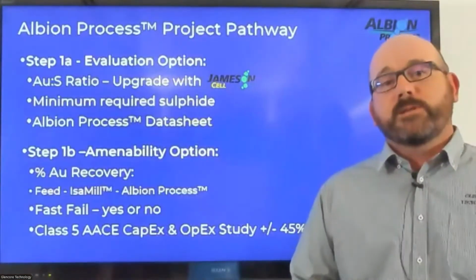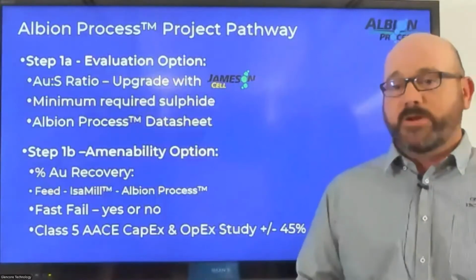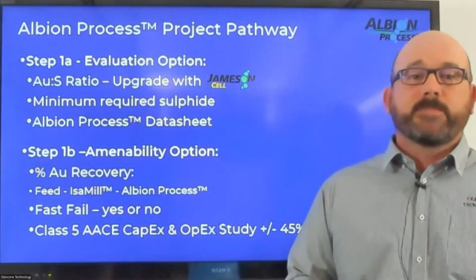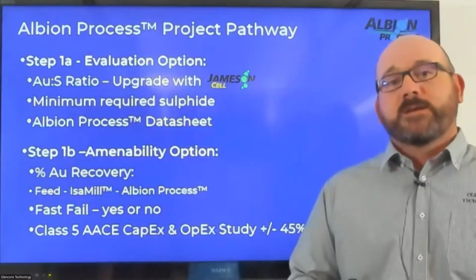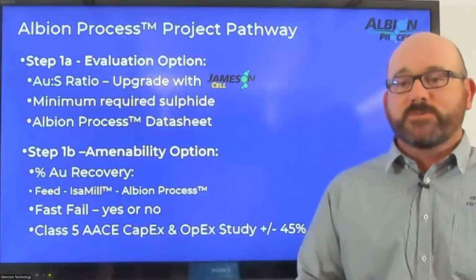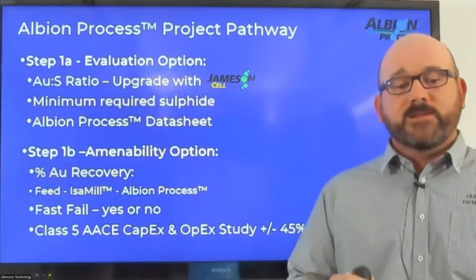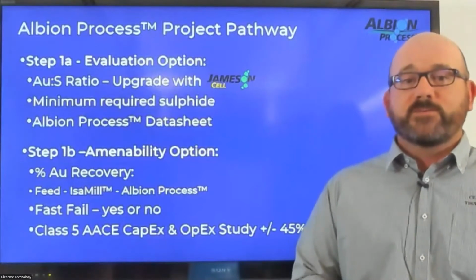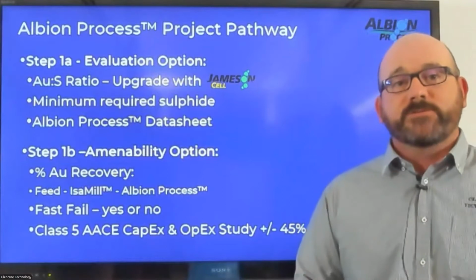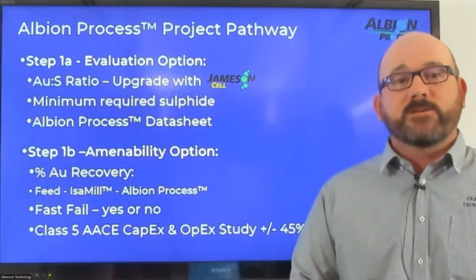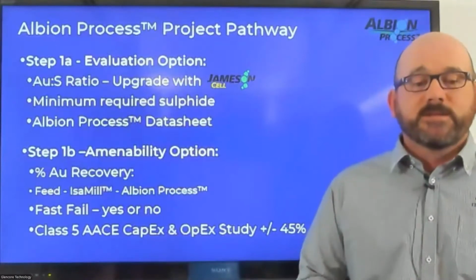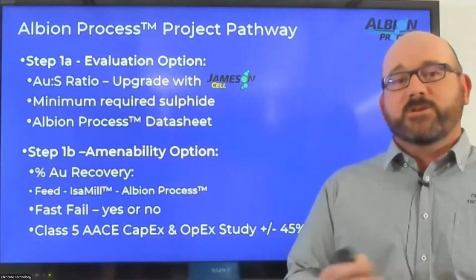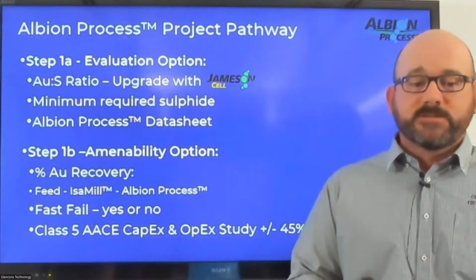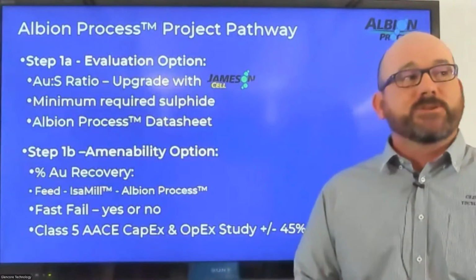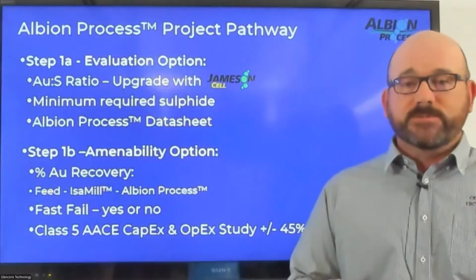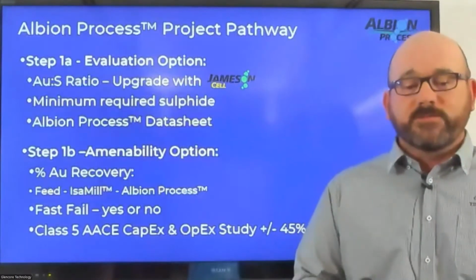So what do we look at to develop the Albion process for your project? Initially, you've done some drill holes and got some cores, and you've managed to find some gold. Then the question is, is that gold recoverable by typical cyanide leaching, or is it refractory? We're concentrating on the refractory gold and trying to assist with recovering that. So what constitutes the value of that? We're looking at how much gold is in there compared to how much sulfide we would need to oxidize to be able to recover that gold and give you the value.